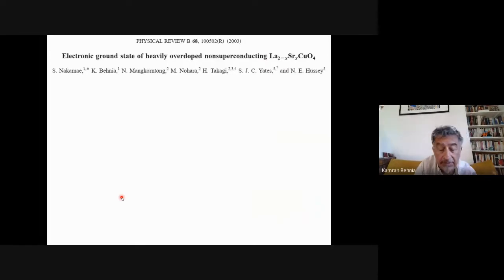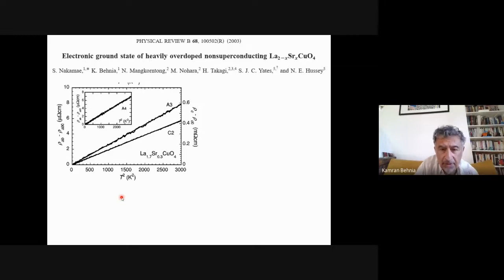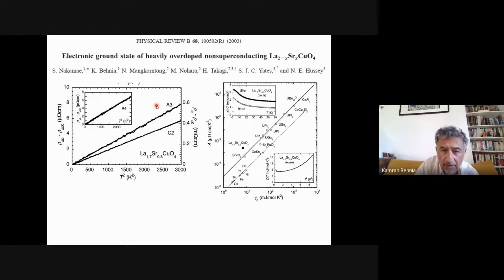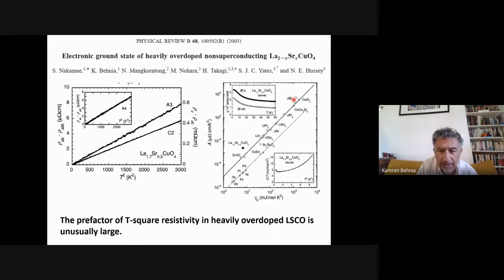Okay, so the reason I'm interested in this is that actually we did this experiment before in 2003. At that time, the paper was not accepted in PRL because people could not believe that it is T-square, but we measured on 2 different samples, and you can see that there is a purely T-square term when you are out of this superconducting dome. There is no superconductivity down to 10 millikelvin. So this is a heavily overdoped LSCO. And at that time, we put it on the Kadowaki-Woods scaling, and you can see that actually it is 5 times higher. But 5 times maybe it's not a big deal. At that time, you can say that it is large, but how large can it be?